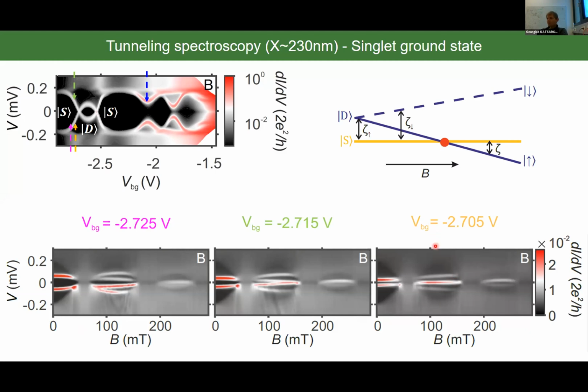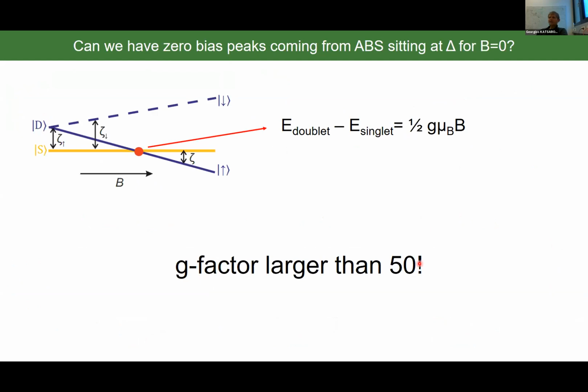The question now is, would it be possible to have a zero bias peak appearing in the first lobe if your Andreev bound states were hidden in the gap? The reason why you can get a zero bias peak here is simply because you need just a very small magnetic field to make them merge. At first glance, you would say it is not possible if your Andreev bound states are hidden in the gap, because if that were the gap, 200 microelectron volt, the condition to get a zero bias peak in the first lobe, which is roughly 100 millitesla, would be that. And this would imply that your nanowires would need to have a g factor larger than 50. And we have demonstrated that our nanowires have a g factor of 10.